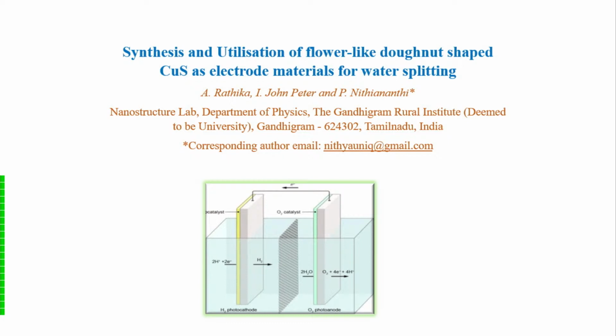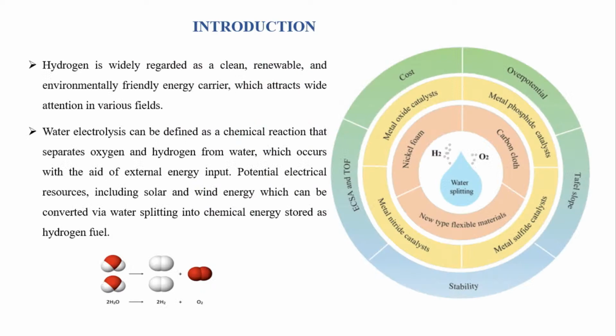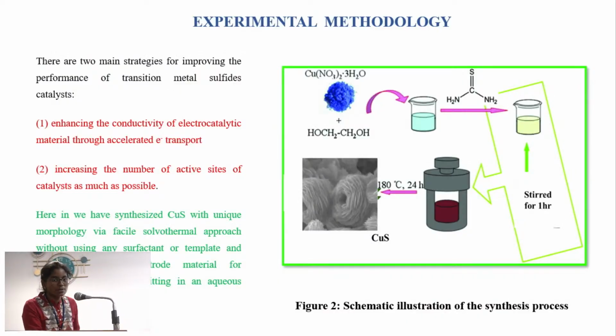Good evening. My topic is synthesis and utilization of flower-shaped copper sulfide for water splitting and other applications. Straight away I go to the experimental technique. Here I have synthesized copper sulfide with flower-shaped morphology without employing any surfactant or templates, using only simple solvents like ethylene glycol and distilled water. One of the two ways to increase the electrocatalytic activity of a material is to make it a composite with carbon-like materials, or to increase the number of active sites of the catalyst as much as possible. Here I have synthesized copper sulfide with a unique morphology via a solvothermal approach.